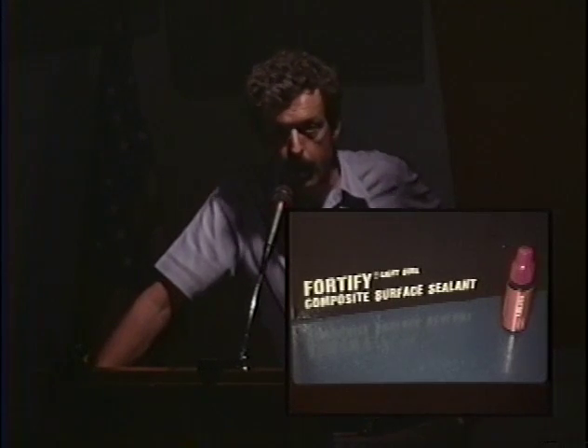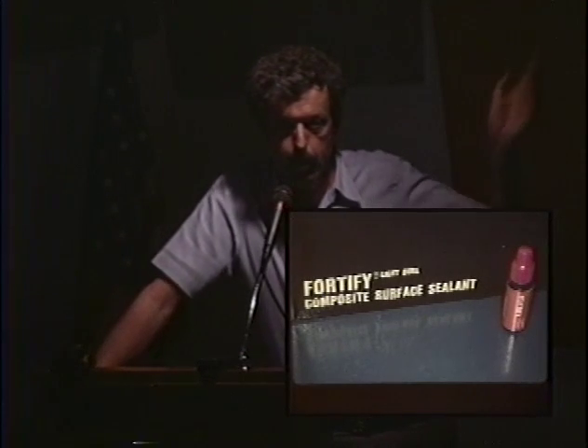Is this used on the occlusal surface only, or box? No, used on every margin. Every margin? Yeah, and on the occlusal, it'll cut the wear rate 50%. If you think that 50% of 25 microns is significant, then go ahead and put it on the occlusal. Can't hurt anything. I mean, it's not enough to worry about, in my opinion.